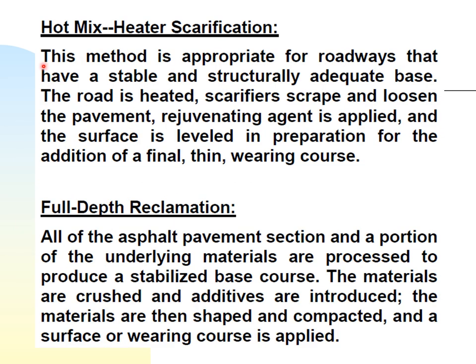On this particular slide, you would find hot mix heater scarification and full depth reclamation. So hot mix heater scarification. This method is appropriate for roadways that have a stable and structurally adequate base. The road is heated, scarifiers scrape and loosen the pavement. A rejuvenating agent is applied and the surface is leveled in preparation for the addition of a final thin wearing course.